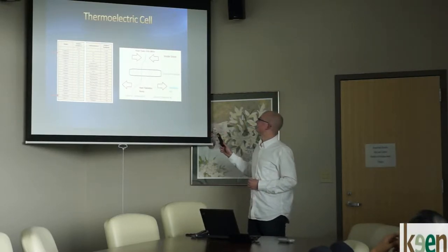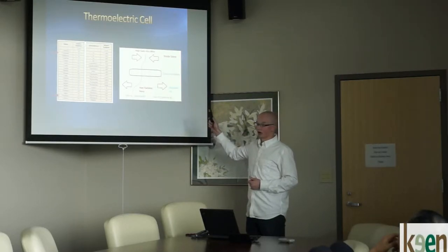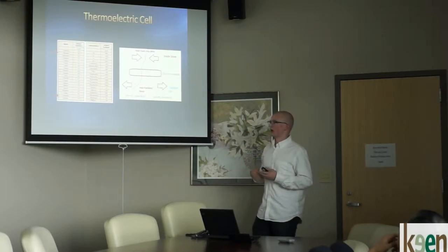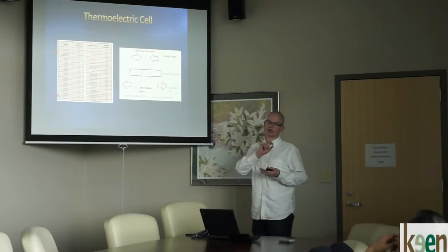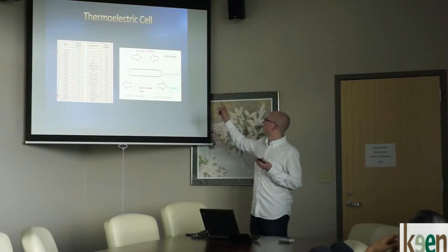On the right-hand side, you see almost the exact setup that I did. I twisted the wires together on the hot end, and then I had them open on the cold end. When I tested it, I actually put about 4 in series just to amplify the voltage a little bit further. Then I used an insulator to keep them apart. I used a tin can, and I used heat shrink to electrically insulate the wires from the tin can. But I did get a good result.